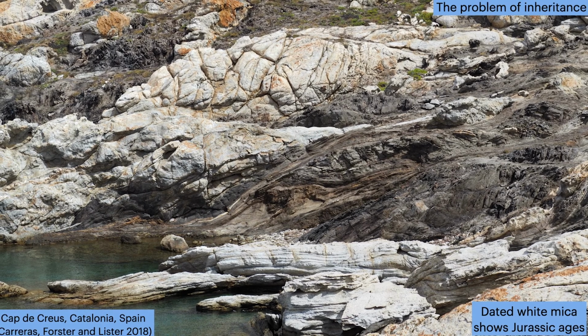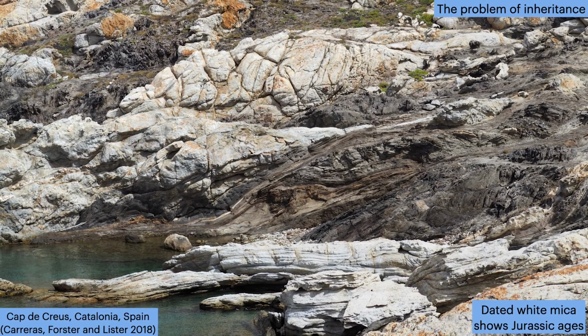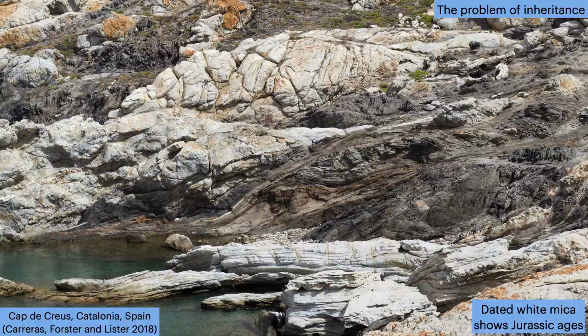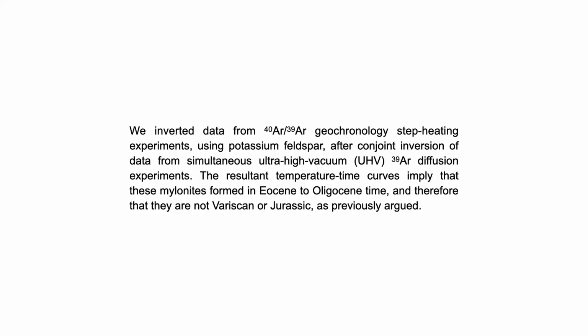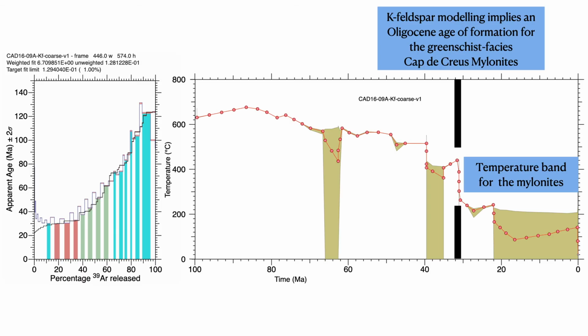to actually date the intense period of greenschist facies movement means we have to overcome the problem of inheritance. And the way to do that is really to date rocks in combination with ultra-high vacuum diffusion experiments. And so we did that with feldspar, and just show you one of the results. And very clearly you can see the age spectrum is complicated. It can be modeled, but the models gave a consistent rapid cooling from about 420 to about 250 degrees shortly after the Eocene-Oligocene transition had taken place.